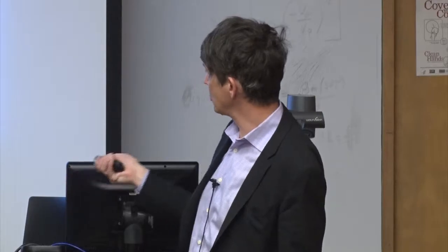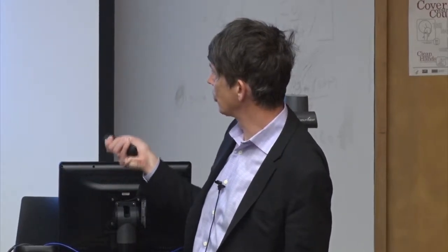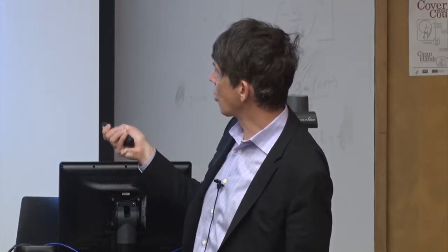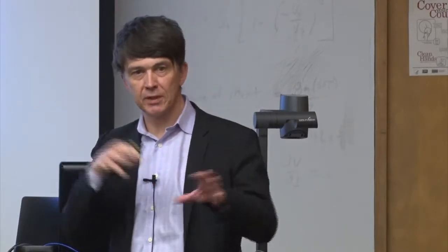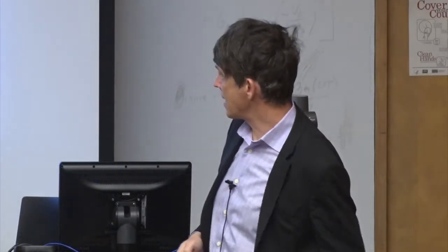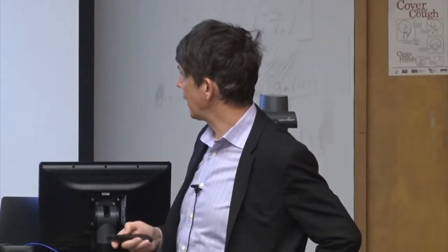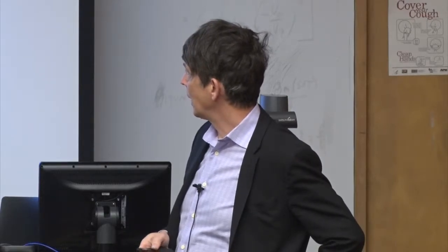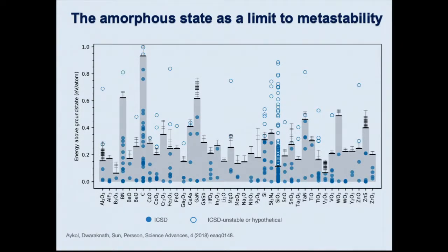So for a lot of different chemistries, they calculated the energy of the amorphous state. The reason that there are error bars is because you do sampling of the amorphous state. It has many different configurations. And then you put on there the energy of the known polymorphs, stable and metastable. And this result is truly amazing. By the way, the solid circles are known polymorphs. The open circles are unknown polymorphs. Every single known polymorph is below the amorphous limit. Every single one. There has been not a single exception to that criterion.